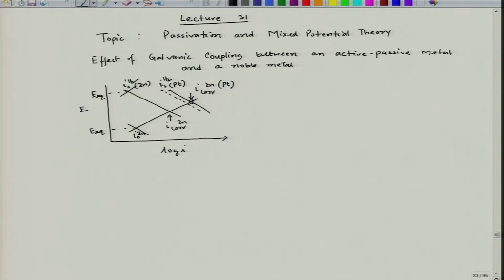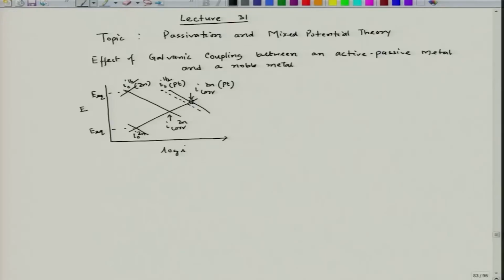But in case of active passive metal, the situation could be different. There could be a situation where the corrosion rate either increases because of galvanic coupling, or there could be a situation where the corrosion rate of the active passive metal decreases largely because of galvanic coupling with a noble metal. So, let us consider the first incident where the corrosion rate of the active passive metal reduces drastically because of the interaction of the cathodic polarization of the reaction on that noble surface with the active passive polarization curve of the active metal on the anodic side.